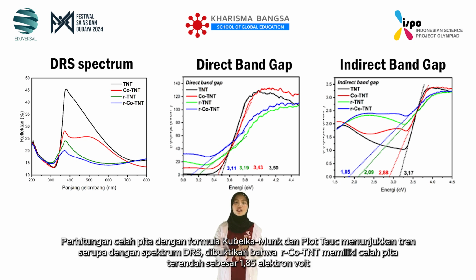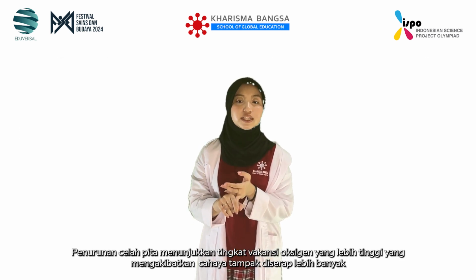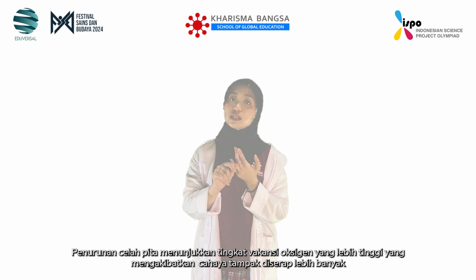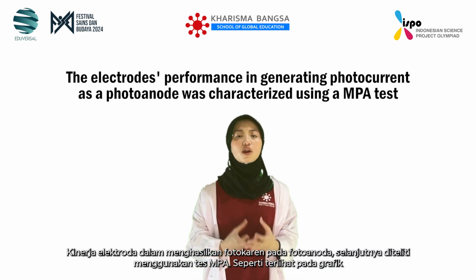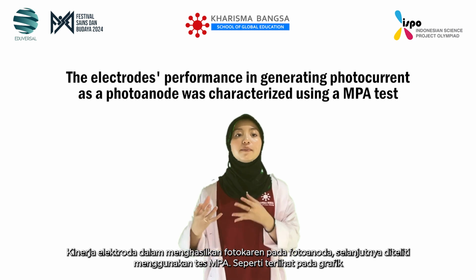The band gap calculation by Kubelka-Munk and Tauc plot shows a similar trend with the DRS spectrum, with RCo-TNT having the lowest band gap of 1.85 electron volt. A decrease in the band gap indicates a higher presence of oxygen vacancy, which leads to a higher amount of visible light absorption. Then, the electrode's performance in generating photocurrent as photoanode was characterized by MPA test, as can be